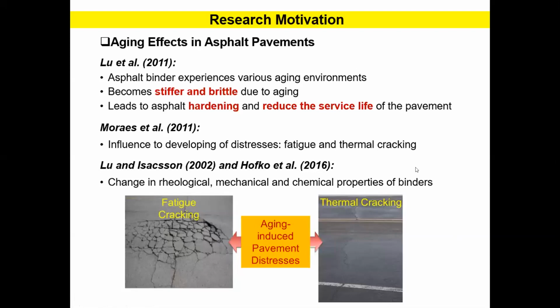You can continue. Well, as you know, asphalt binders experience different kinds of aging during field conditions, and over time it becomes stiffer and brittle, which leads to asphalt hardening and reduces the service life of the pavement. However, it is also found that aging can influence the development of different kinds of pavement distresses, including fatigue and thermal cracking. Here you can see in the picture, the left bottom is fatigue cracking, and the right one is thermal cracking. It is also found that aging can change the rheological and mechanical as well as the chemical properties of the asphalt binders.